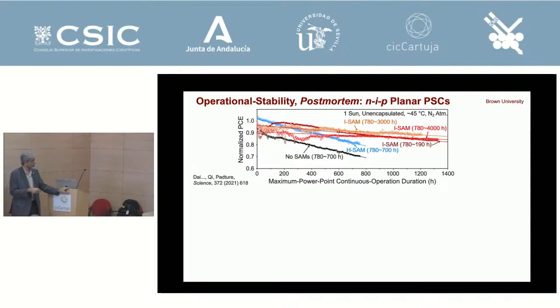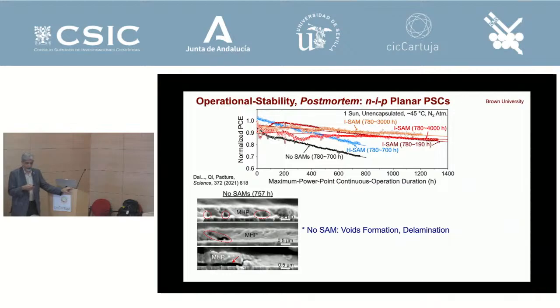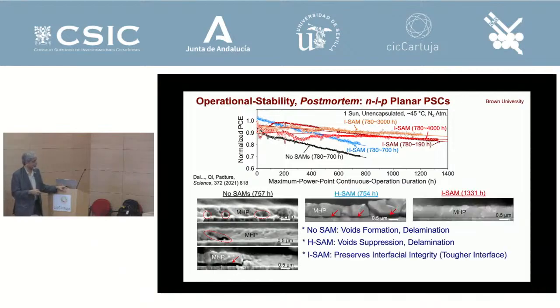Sorry, this should be 1900 here. So it's 4,000 hours, right? And if you look at the solar cells after testing, you take it apart and you look at it, you'll find that there are voids and delamination. I won't go into this, but when you have the SAMs, you can see that after the testing, the interface is relatively pristine, which is why the solar cell is lasting longer.